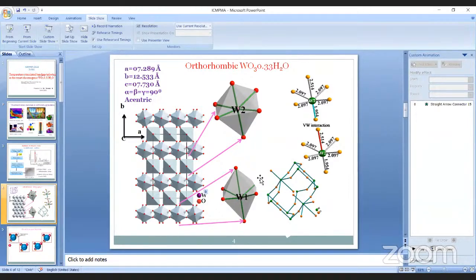Then this is the Rietveld refined structure of this material at room temperature. And this is the polyhedral structure of the sample. The polyhedral structure consists of two types of WO6 octahedra. In the WO6 octahedra, the tungsten atom is at the center, surrounded by 6 oxygen atoms. And between these two WO6 octahedra, there is a water molecule present.